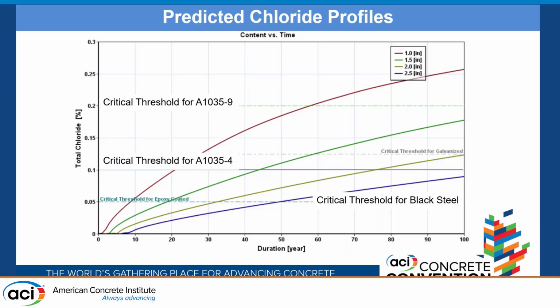I have a line for galvanized here. Galvanized bar would get you up to about there, and then this line here is for the A1035 at 4% chrome. And here's your black steel, and epoxy has a longer. It has basically the same threshold value, but it goes out a little bit longer with propagation time.